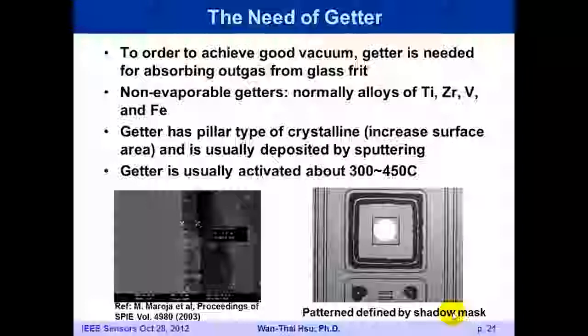And that follows the need for getter, and there is basically one getter company in the world. And is there any sales guy here? Okay, so I will not offend anyone then. They basically have all the patents. In order to achieve good vacuum, getter is needed, and the composition of getter is titanium, zirconium, vanadium, and iron. And they deposit this type of material into a kind of pillar-type crystal,